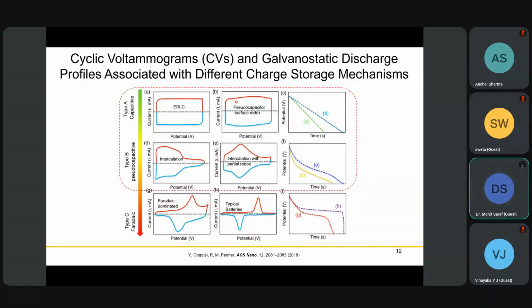On the other hand, for the pseudocapacitor, you will see a quasi-rectangular shape in the CV profile. In the case of batteries, dominated by a Faradic process, you will see very sharp peaks at one particular potential, and you will see plateaus in the charging-discharging curve. These are typical of batteries.